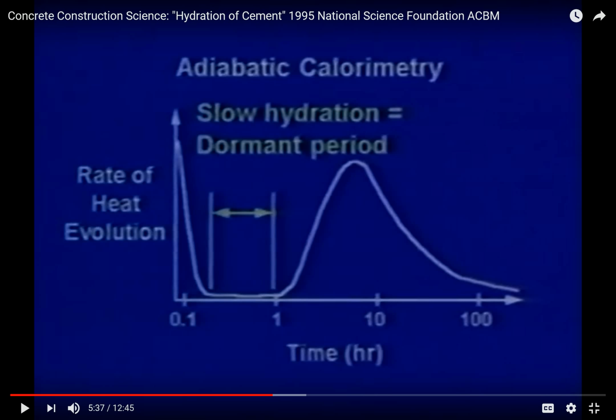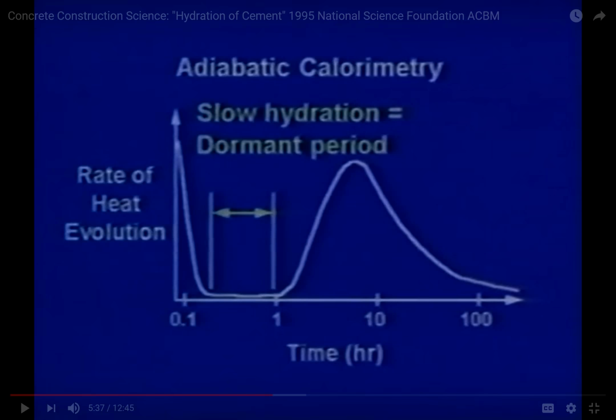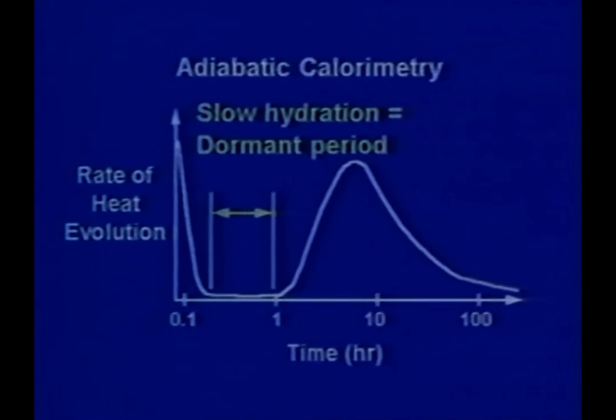So in the beginning, when you have this hydrated layer, after a while, since you have a protection around the cement particles, the reaction slows down. And this is the time when you would transport the material from the plant to the job site without the material sitting in your truck. So if you didn't have that, then you would get to the job site and you couldn't empty the truck because it was already hardened. So it's super important to know this shape and these characteristics of how each cement hydrates, and we know that from the rate of heat release. The existence of the dormant period allows concrete to be transported through the construction site and placed and finished in the molds.